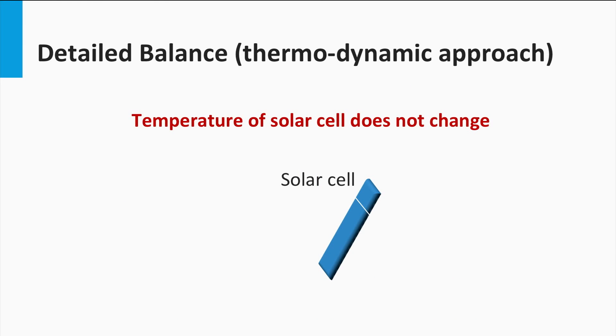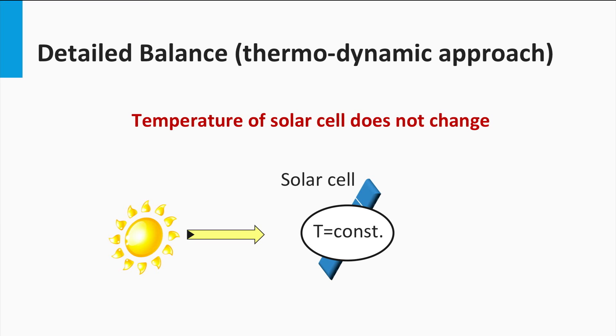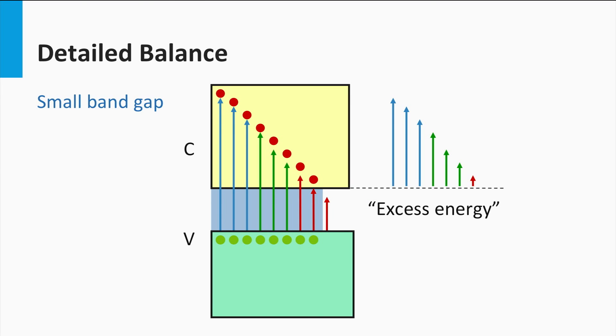This means, in a very simplified picture, we make a thermodynamic approach of the solar cell. We have the AM1.5 spectrum incident on a solar cell and we don't allow the solar cell to increase in temperature. This means that all energy in the incoming AM1.5 spectrum can escape the system either as current density generated or by the radiative recombination of charge carriers. For a low band gap material, the energy lost below the band gap is moderate; however, the amount of excess energy of the energetic photons is significant, and this energy has to leave the system through radiative recombination.